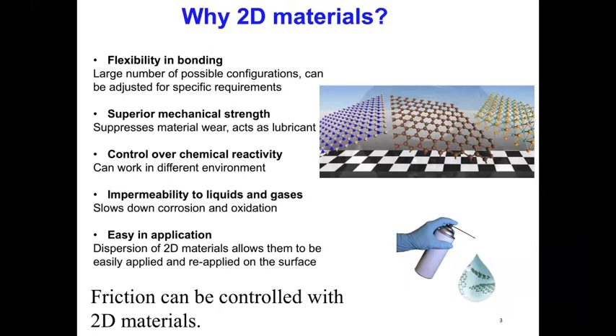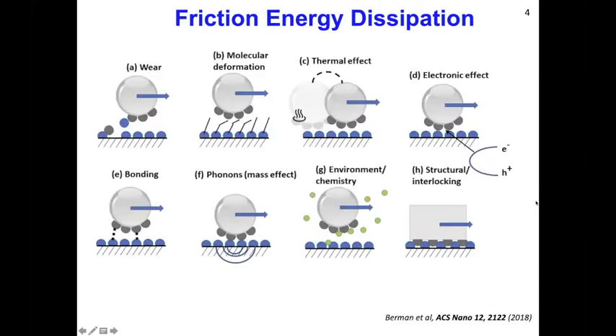So if you compare to any other coatings which we know, such as PVD and CVD systems, they usually require a more complicated process: disassembling the whole mechanical assembly and putting it into vacuum chambers under high temperature conditions, under plasma. That complicates the whole idea of replenishing the coatings and using them for more robust systems. With the easy application idea, we looked at whether we can use this as a spray coating or injection, whenever there is a need to replenish it quickly on the sliding surfaces. Thus, the friction can be controlled with these two-dimensional materials depending on the requirements and needs.